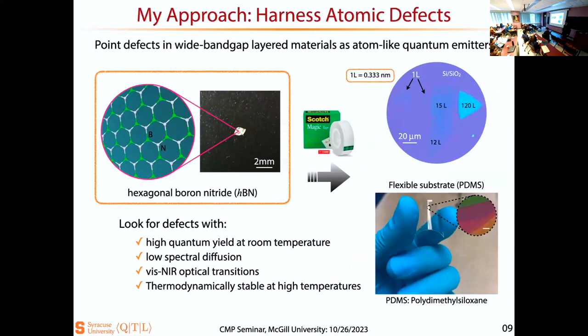The size of the defect matters. Size, okay. A defect is always an atomic defect. Now elaborate on your question. What do you mean by the size of the defect? So a defect could be, let's say, a boron is missing or substituted by oxygen. Then you can have either a vacancy there, or because of the difference in the bonds they can form, that acts as a localized defect. And if they are luminescent defects and you pump them optically, they emit light in visible to near infrared. So those are really atomic defects.